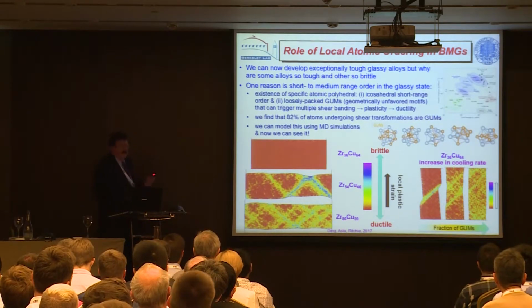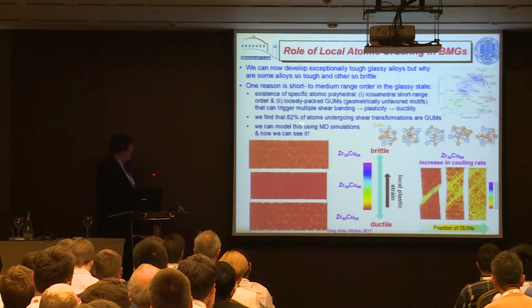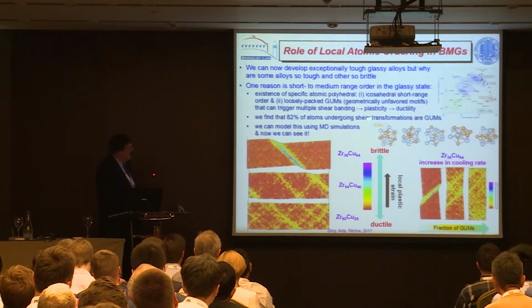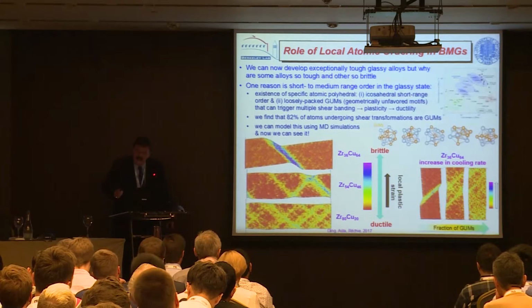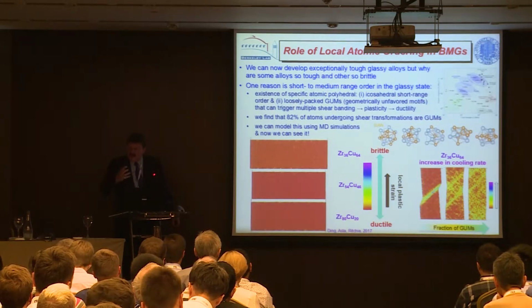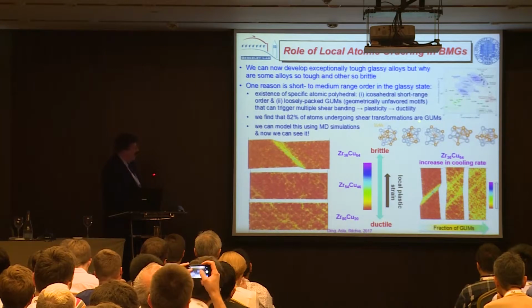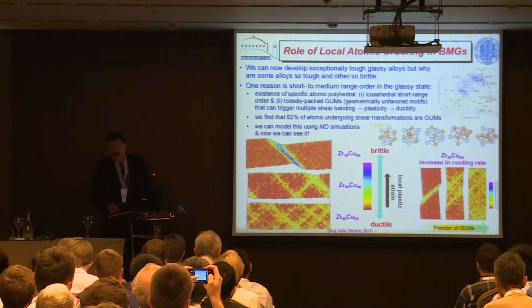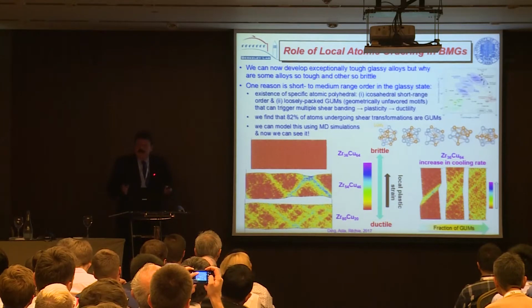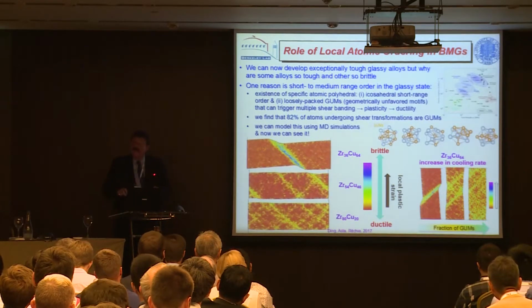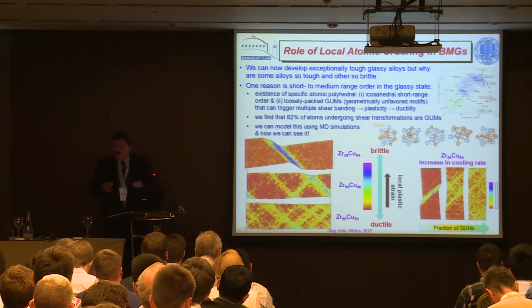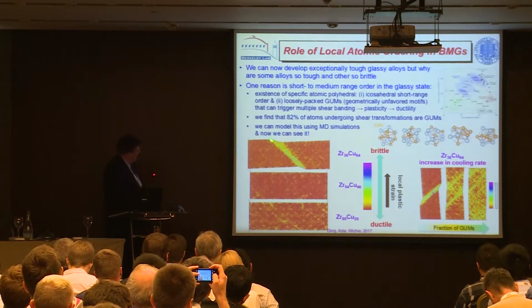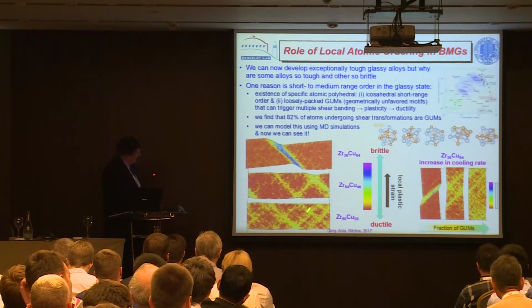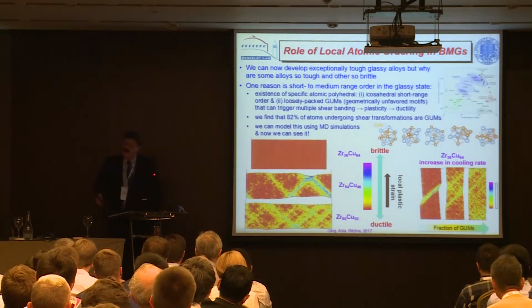And if you do that, this is all done by MD and DFT calculations. If you do these calculations, we find that 82% of the atoms involved in shear transformations, that's the shear bands which cause the plasticity, which is the essence of toughness in these glasses, are associated with GUMs. So I liken this to you basically discovered the equivalent of grain size in an amorphous material. If you can build in a homogeneous or a wide distribution of these GUMs or less stable local symmetry, you can generate not a single shear band, which gives you very low ductility, but multiple shear bands that give you plenty of ductility and toughness.